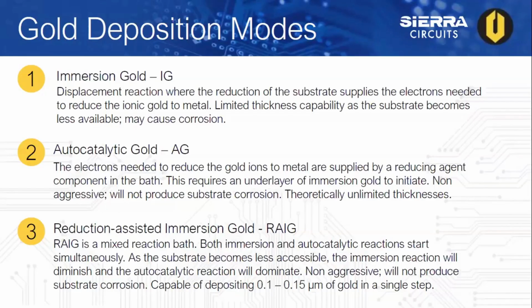Three, we have reduction assisted immersion gold, also known as RAIG. It's a mixed reaction bath where both immersion and autocatalytic reactions start simultaneously. As the substrate becomes less accessible, the immersion reaction will diminish and the autocatalytic reaction will dominate. It's non-aggressive and will not produce substrate corrosion. It is also capable of depositing 0.1 to 0.15 microns of gold in a single step.